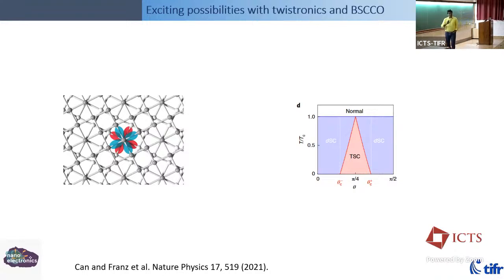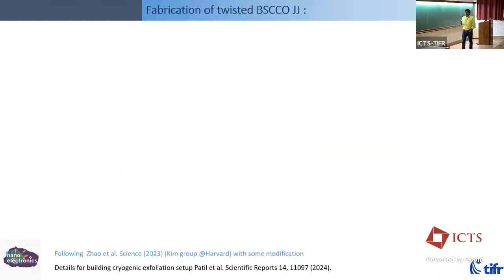Yeah, so their proposal is that when you have this co-tunneling of Cooper pairs, then you can get these two possible states, circulating in one way or another at the interface. So it's an interfacial superconductor with time reversal symmetry broken. Okay, so that sort of got us also interested, and one of the few people to start working on BSCCO very early on was Philip Kim's group at Harvard.